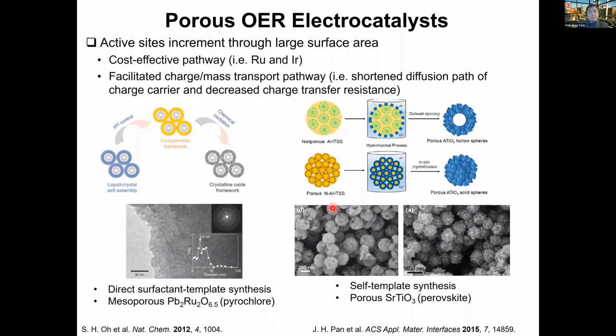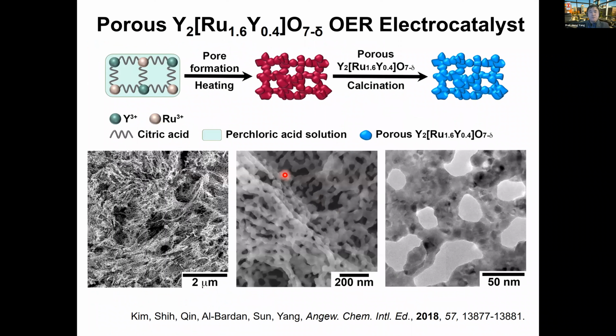What we have found is that we can also generate pores by having a porogen. In this case, it is perchloric acid. If you use perchloric acid in this particular system, we can actually generate a very porous, literally ceramic-type structure made of yttrium, ruthenium, and oxygen. So this is a porous structure. As you can see, the mesopores are connected through the primary particles.